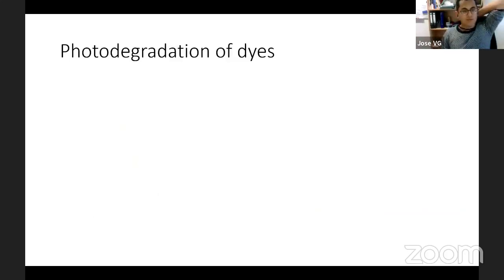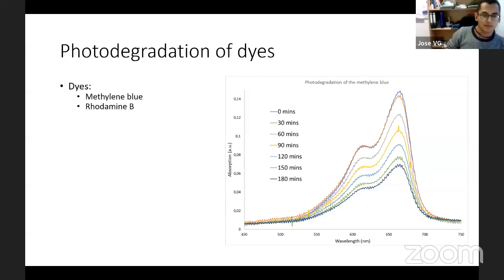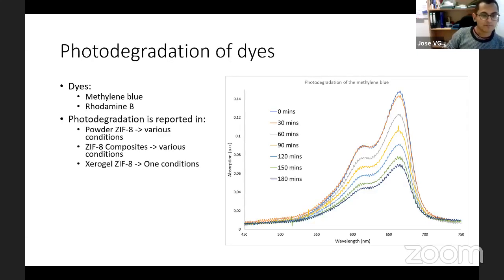So this material has been used for photodegradation of dyes, especially methylene blue and rhodamine B. It has been reported for the powder a long time ago at different conditions, and it also has been reported for the composite in powder form at different conditions. The xerogel has been reported, but only at one condition. All the different pH, different concentration of the dyes, different concentration of the ZIF-8 has not been reported. And so the current students, the practicants who usually come every month to my lab, I usually give this kind of work and make a small publication where they can also participate.